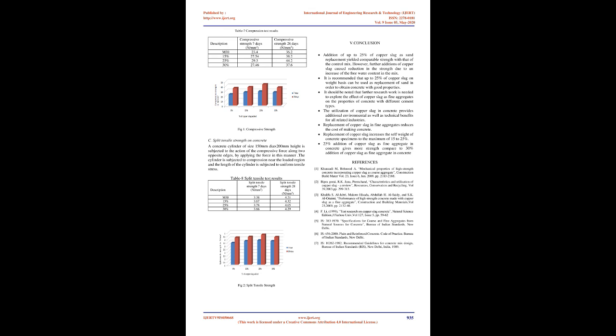The utilization of copper slag in concrete provides additional environmental as well as technical benefits for all related industries. Replacement of copper slag in fine aggregates reduces the cost of making concrete. Replacement of copper slag increases the self-weight of concrete specimens to the maximum of 15 to 25%. 25% addition of copper slag as fine aggregate in concrete gives more strength compared to 30% addition of copper slag as fine aggregate in concrete.